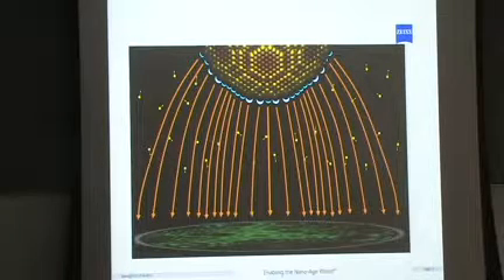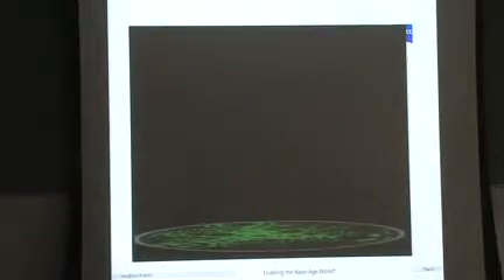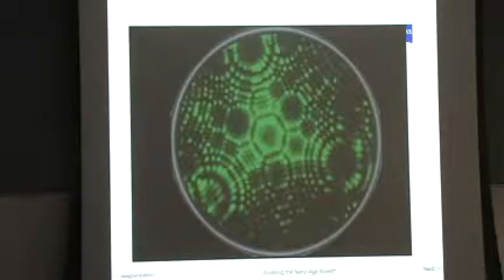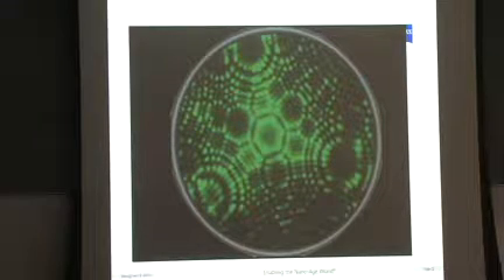So you'd put a screen under here, a microchannel plate or a phosphor at the time, and if you take a look at that pattern, it looks like this. So this is the piecewise approximation to a spherical end form from a crystalline lattice of atoms. And each one of these little points is an atom on the tip. So right away you can tell these beamlets are originating from something the size of angstroms or perhaps even sub-angstroms.